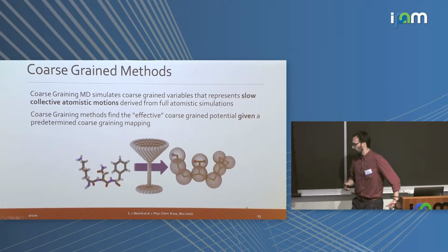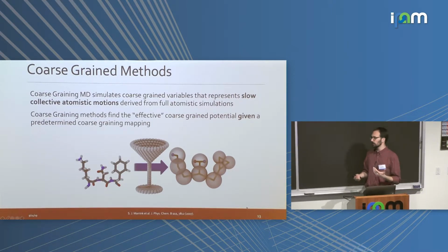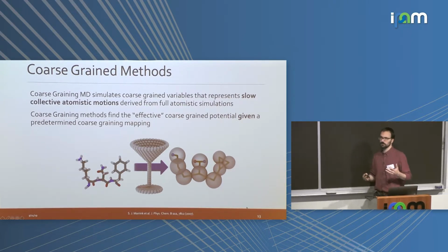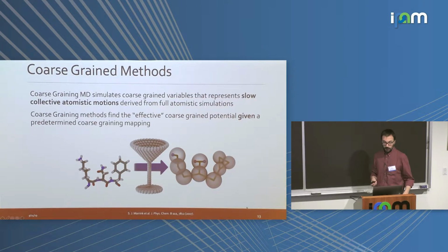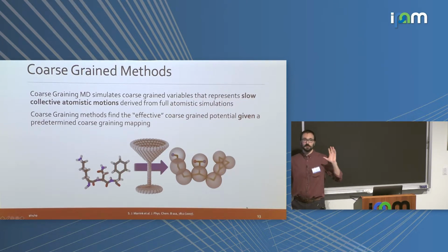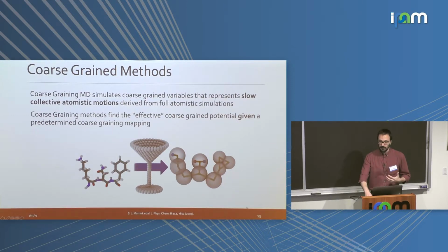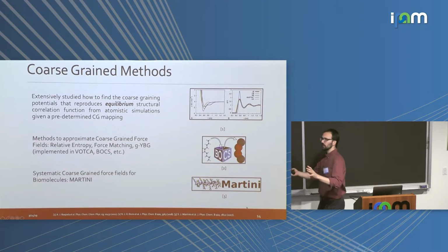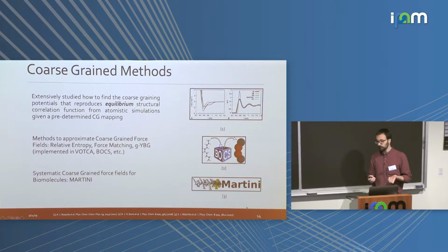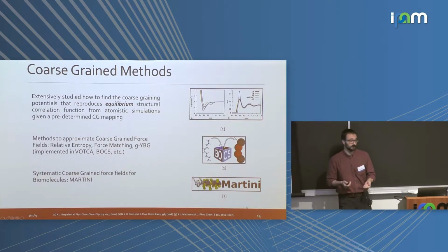Imagine, like when you're maybe crystallizing a polymer, melting a solid. The length scale of those processes is something we cannot get to with simulations for most problems. And the way people address this problem is what they call coarse-graining, which is deciding, I'm not going to simulate all the atoms that make up my system. I'm going to assume that some of them move collectively, and that I can suppress their collective motions and represent the set of connected atoms with one superatom, with one bead. And we typically do that so that we reproduce the structure of the system we're trying to study.